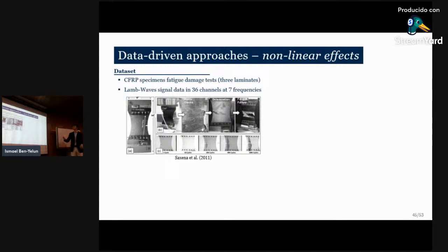Now we will use it in some fatigue damage tests, specifically for CFRP composites. This data set was provided by NASA, and on top of this fatigue damage test, we are performing some measurements with a non-destructive technique, such as Lamb waves. So we will take our healthy specimen, do some measurements with the Lamb waves, then put it in the test machine, perform some number of cycles, and then retrieve it every certain number of cycles to perform more measurements.